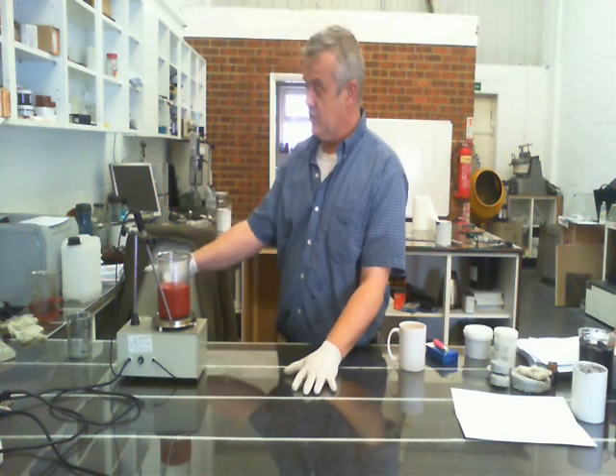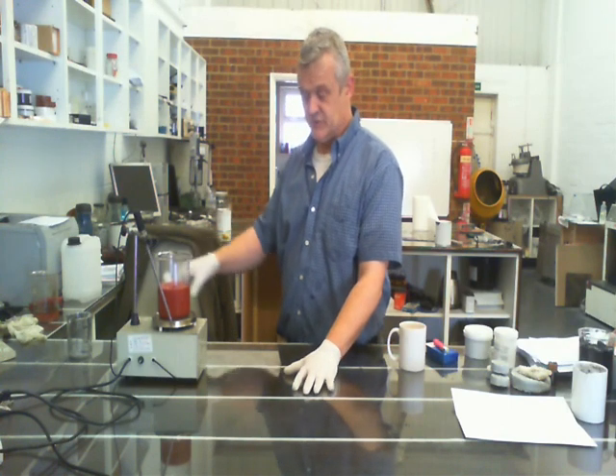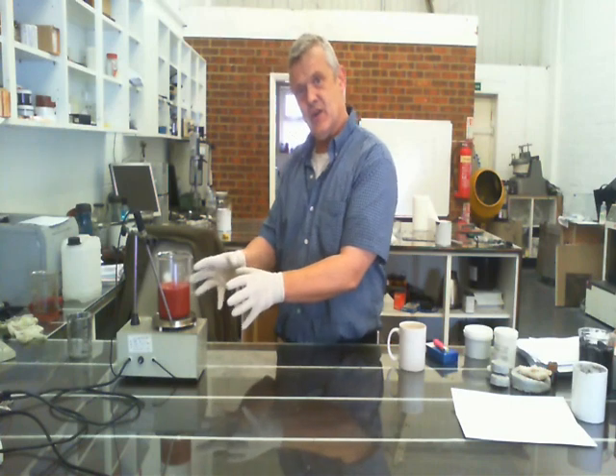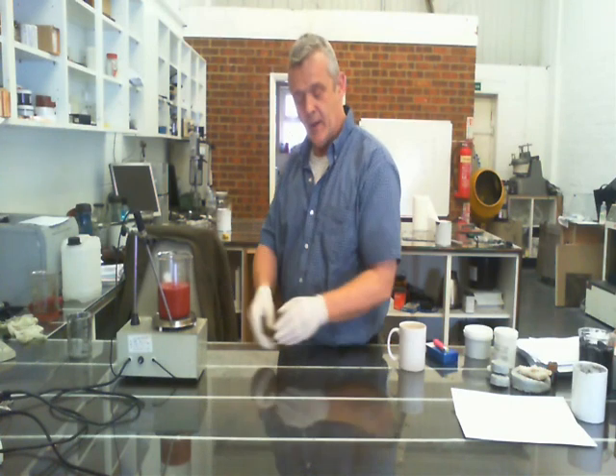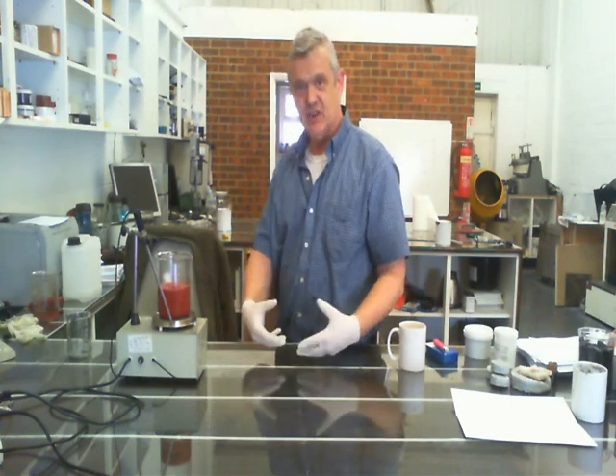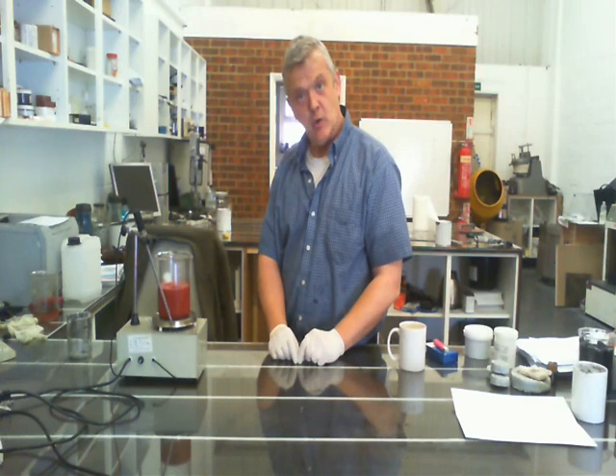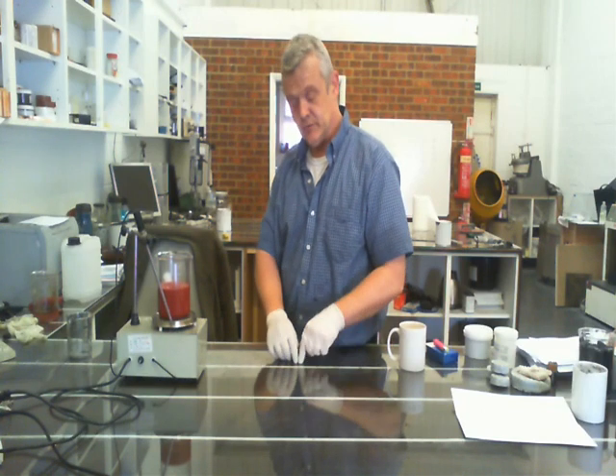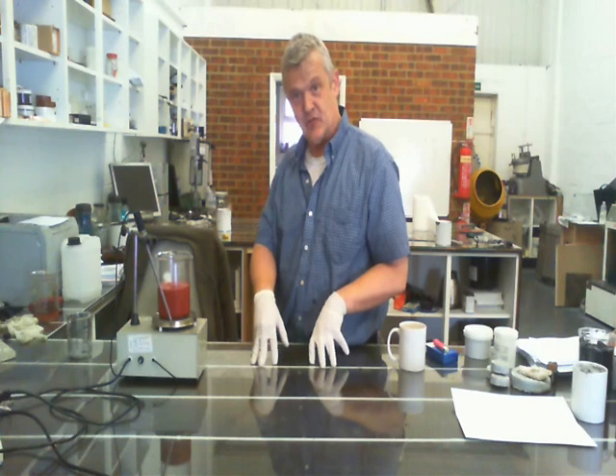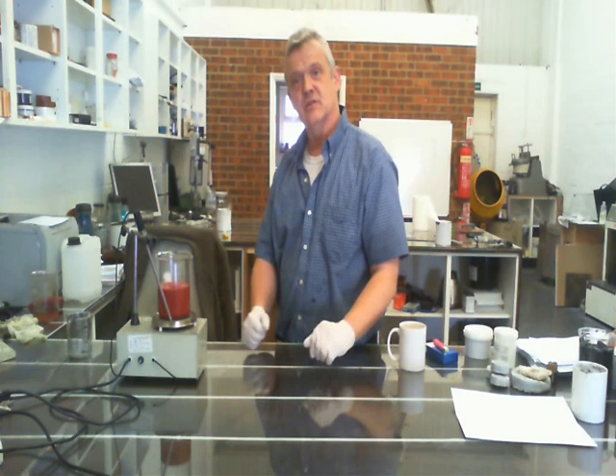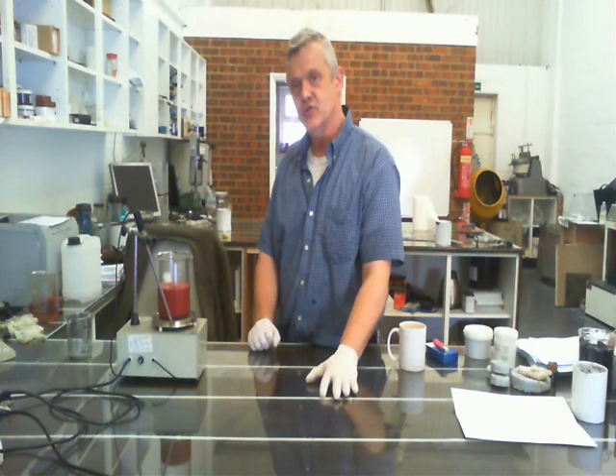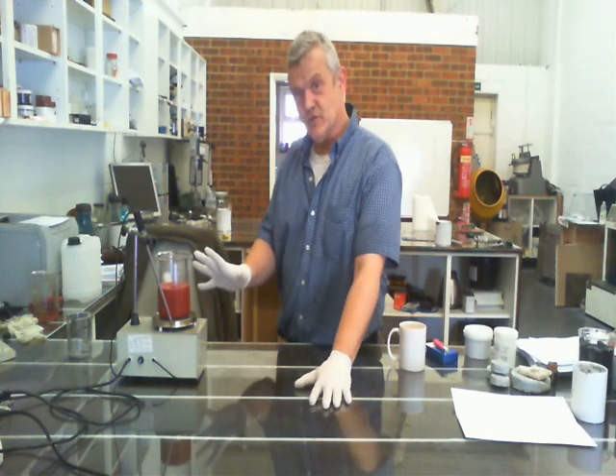So we've got water dispersible copper nanoparticles, and it doesn't really matter if there's any copper formate still left in there, because you paint it on, flash it, then the copper will grow, starting from the copper nanoparticles, into the next copper nanoparticle, sintering it as a conductive track. So that's why I've used copper formate, and it works really, really well.